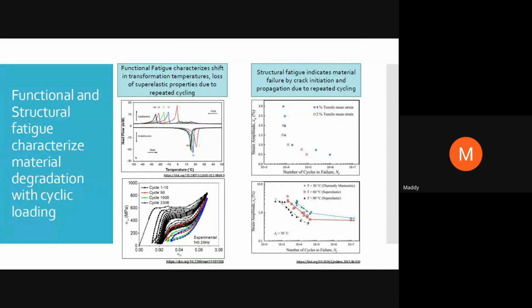and what factors it depends on. So starting with functional fatigue, as the name indicates, functional fatigue means your functional property, your shape memory or superelastic response, gets degraded due to repeated cycling. So if you look at the DSC, the thermal chart on the top, you can see that as you start from cycle 1, which is the red profile, a thermal profile, you will see that it starts at a higher temperature, and with cycling, the phase transformation from austenite to martensite, which is on the cooling, shifts towards lower temperature. And I must say that the axes have changed here compared to the previous DSC. You can see that the cooling is actually the top profile and the heating is the bottom profile. Okay.